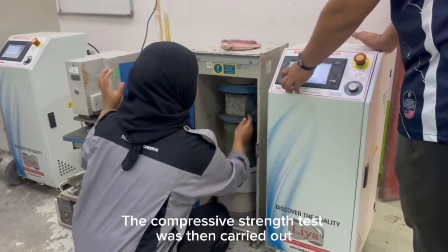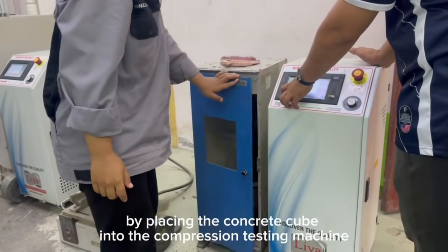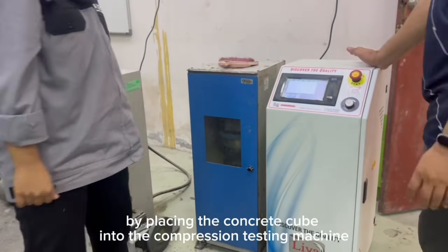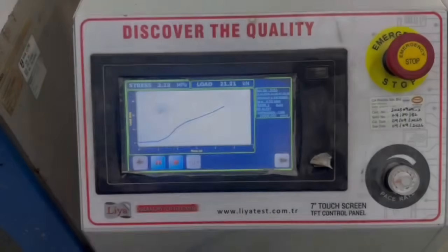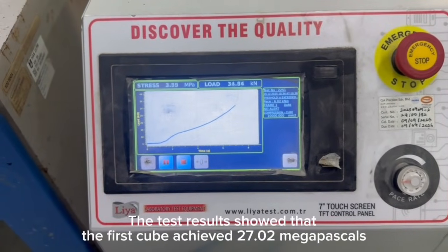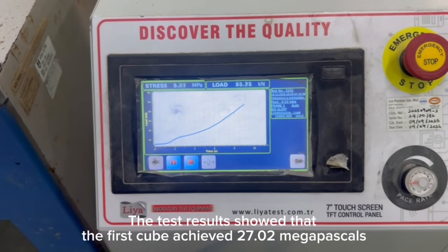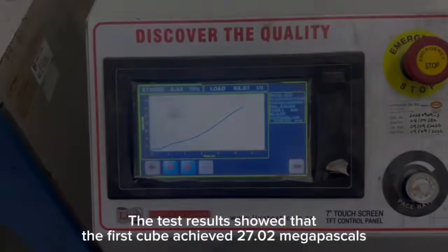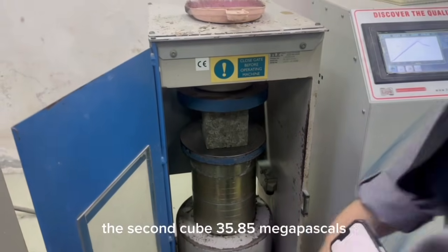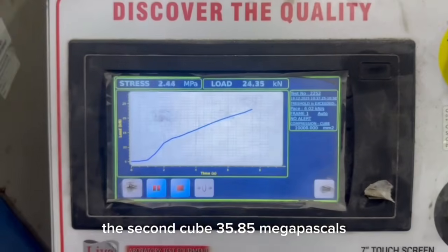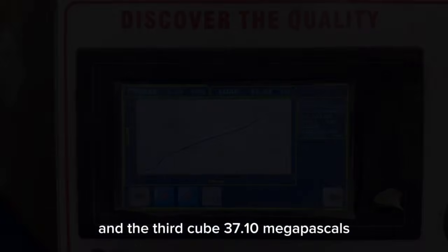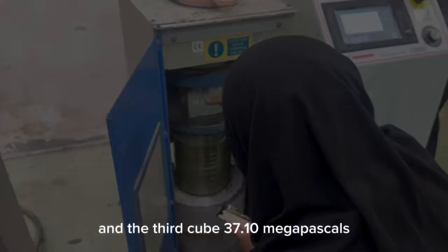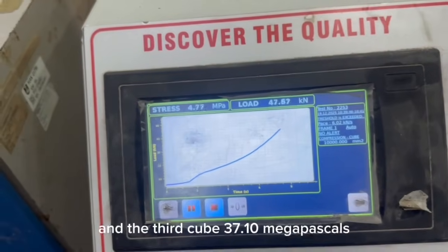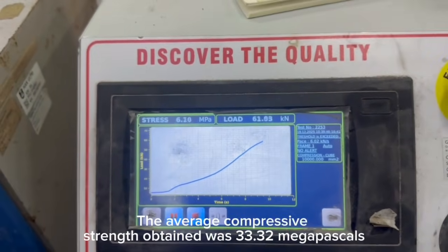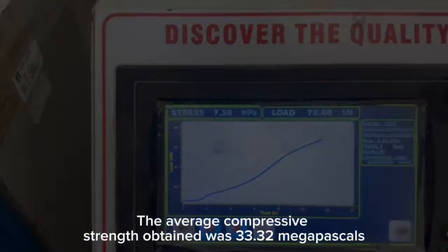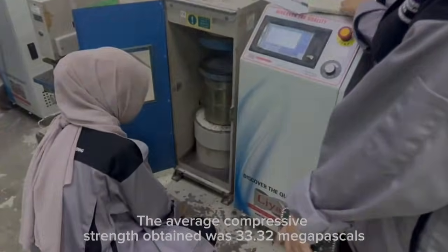The compressive strength test was then carried out by placing the concrete cube into the compression testing machine. The test results show that the first cube achieved 27.02 megapascal, the second cube 35.85 megapascal, and the third cube 37.10 megapascal. The average compressive strength obtained was 33.32 megapascal.